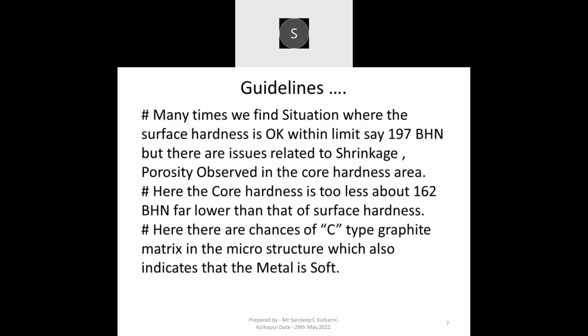Here, there are chances of C-type graphite in the microstructure matrix as well, which indicates that the metal is soft in nature. Because 162 BHN is the hardness at the core, we can find C-type graphite in the microstructure matrix. It indicates that the metal is soft. This data is from the OEM representative, where the problem has been there. The same data I have taken here, so it is a true case study, you can say. A gap of around 35 BHN is there, and they have observed C-type graphite as well as open grain structure, some shrinkage and microporosity in the casting while machining.